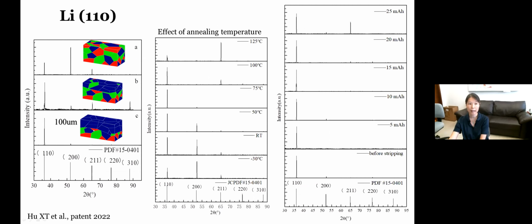And I have to say that the temperature for the recrystallization is very, very important, as shown in the XRD results in here. So at low temperatures, if the temperature is getting lower and lower, you see predominance of the 200 diffractions in the X-ray. But if you move to even higher temperatures, you see the diffraction of the 211 start to grow. And only at about 75 degrees will we be able to get a very nice surface texturing of lithium 110. And then again, by a similar method, we estimate the thickness of the surface texturing is about 100 microns without considering the X-ray attenuation, right? So this is thicker than that one.